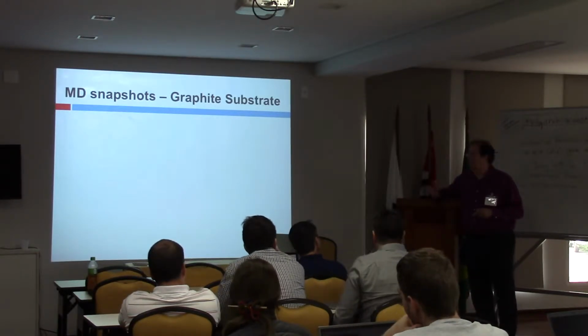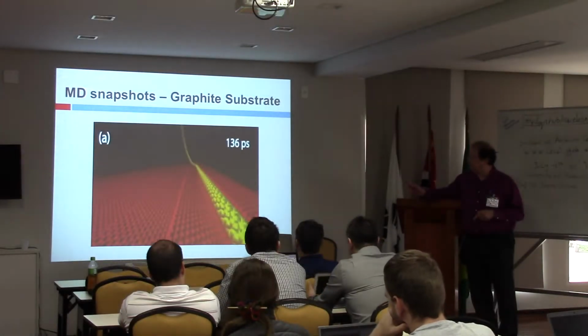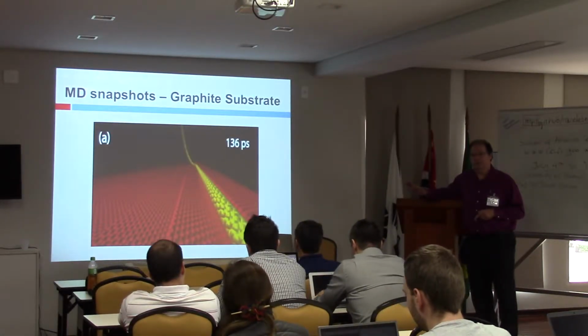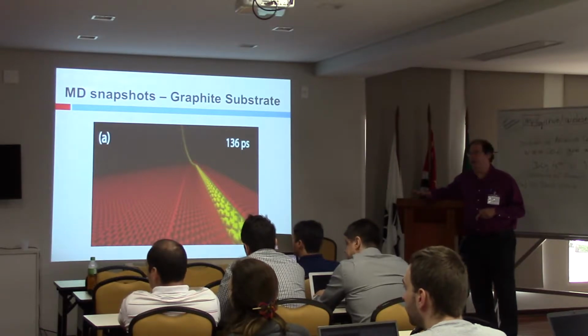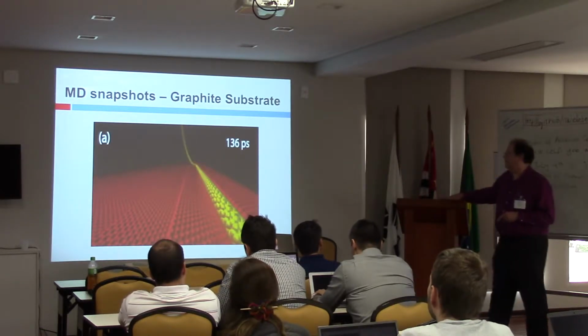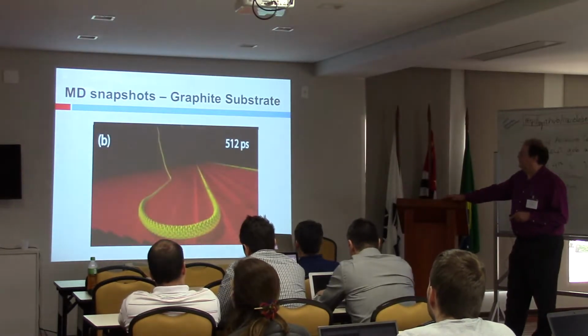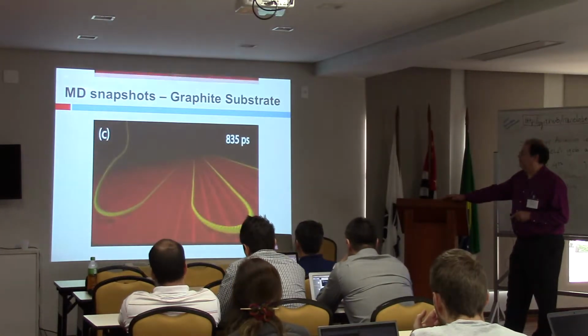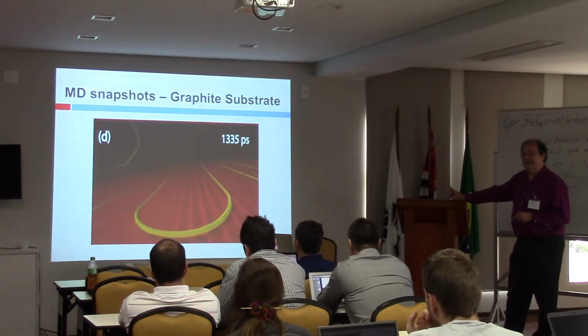Very, very nice. One question is how important is the substrate? So we redid the simulation, but using graphite, the graphite substrate. It's not possible to create that substrate experimentally. It's just to prove the concept that the steps are more important than the material of the substrate. You see the formation, it's almost the same, but the dynamics is different.